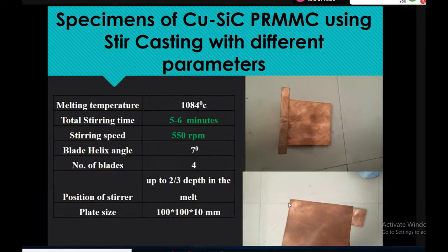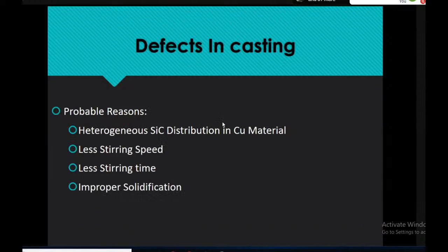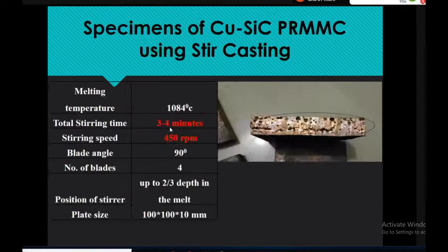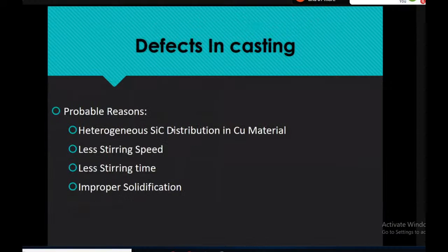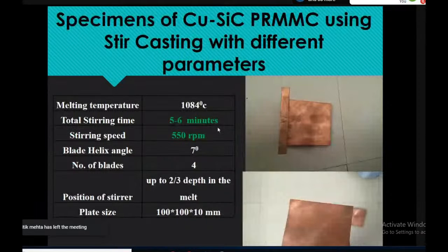Now the melting temperature of copper, that is not going to change. That is same while we change the stirring time. Now we stirred about 5 to 6 minutes. So initially it was 3 to 4 minutes. Now that we have changed to 5 to 6 minutes. We also changed the stirring speed. It was 450 rpm. Now we performed the experiment using 550 rpm.